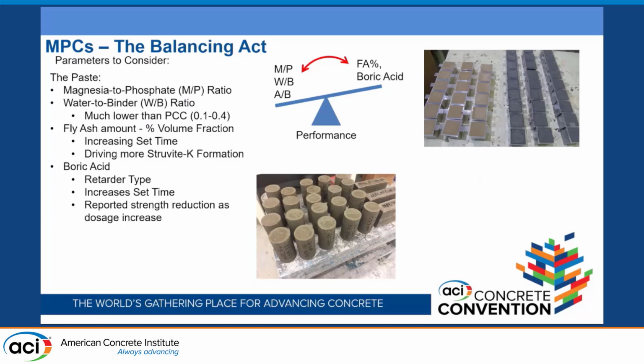So the balancing act I was talking about is mostly about the paste right now. There's big things in the literature. You're going to see your magnesium to phosphate ratio. A lot of people give that to you in molar ratios. You can get it in mass ratios, however you want to do it. Your water to binder ratio is typically 0.1 to 0.4.